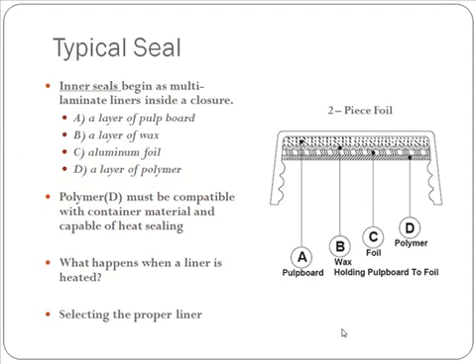This picture depicts a typical two-piece induction liner inside a cap. The first layer up inside the cap is a pulp board. This pulp board is bonded to the foil with a layer of wax in the middle. Then you have your foil, and underneath that foil a polymer layer. This polymer layer must be compatible with the container material. When the liner is heated, we send out an electromagnetic field that vibrates the foil, heating it up. When the foil heats up, the layer of wax melts and absorbs into the pulp board, separating the foil from the pulp board. The polymer layer also melts, and that is what creates your hermetic seal, sealing to your bottle. When all is done, the wax is up in the pulp board, the cap separates, you have your foil left on the container, and the pulp board is left in the cap.